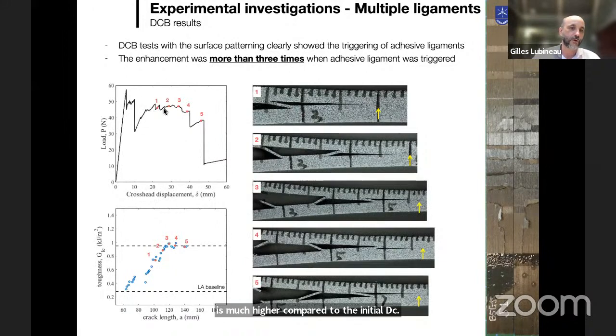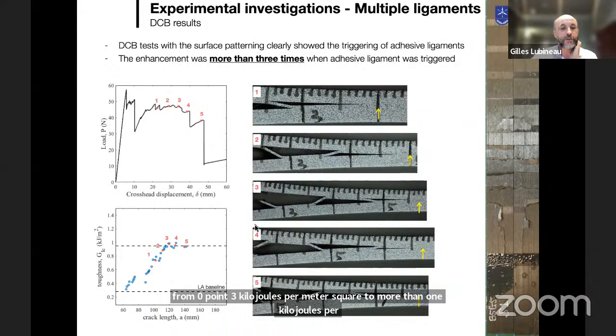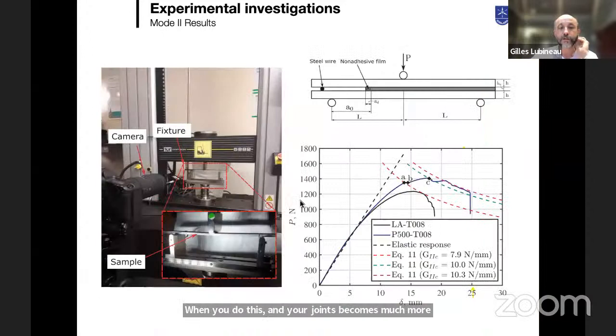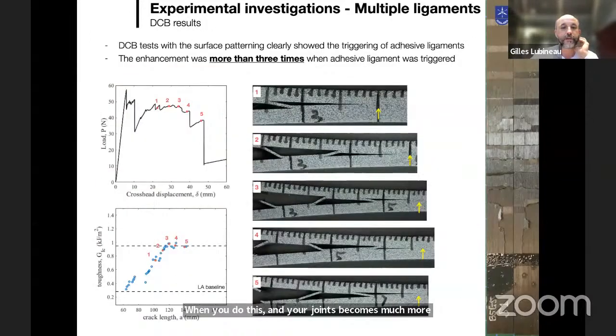So you see a lot of crack jumping events here that are all related to the formation and breakage of different ligaments, 1, 2, 3, 4, 5. And if I look at the apparent toughness of the system, this is very important. The apparent toughness of the system is going to increase by 300% because you will jump from 0.3 kilojoule per meter square to more than 1 kilojoule per meter square. So you have a huge improvement of the performance of your joint when you do this, and your joint becomes much more stable. Okay. So this is something that I presented here in mode 1.